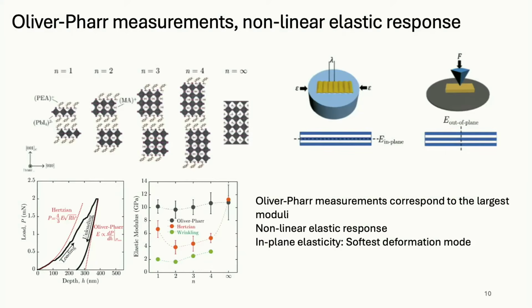When you do this sort of nano indentation, you can start with the tip at the surface and then embed it, and you'll increase the load, and you'll go to a greater depth, and then you could start to take the load away, and the tip will come back out. And so there are 2 different ways that people can yield elastic moduli from this. One is to look at the curvature right when you're entering the material, and that's referred to as the Hertzian regime. You can see here fitting this to like a parabola. And then taking the slope of the unloading regime, you can get an elastic modulus as well, and this is referred to as the Oliver-Pharr approach.